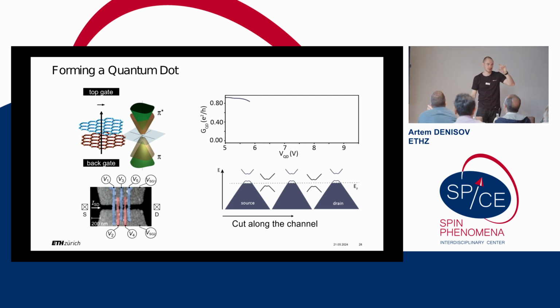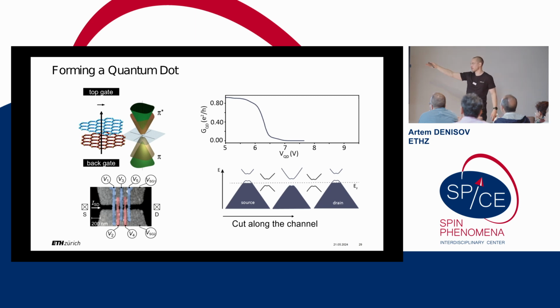What the finger gate does is tune the chemical potential underneath it very locally, by means of a field effect. So imagine that you apply negative backgate voltage, so you accumulate holes everywhere in the device. Then you define the 1D channel, and then you start to apply positive voltage to one of the finger gates. When your carrier gas under the finger gate is the same, also P, holes accumulated, you will just see some conductance flowing through it, nothing spectacular. However, as you go more positive and move your Fermi level into the gap under your finger gate, your current, of course, will go to zero.